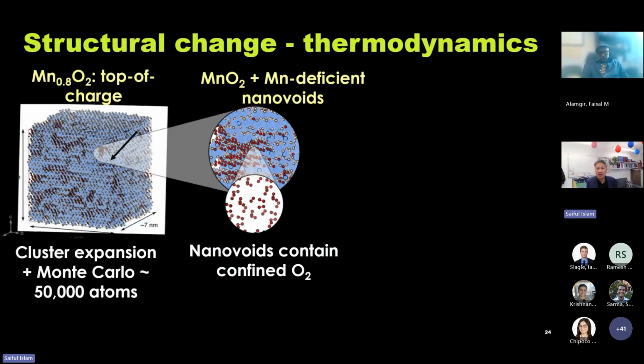So the next thing we did is, what about the thermodynamics? That's kinetics. The thermodynamics. So again, I'm showing you on the left what's happening at the top of charge when we've taken out a large amount of lithium, 1.2 lithiums per formula unit. And this is using what I mentioned before, this cluster expansion approach and Monte Carlo, using more than 50,000 atoms.